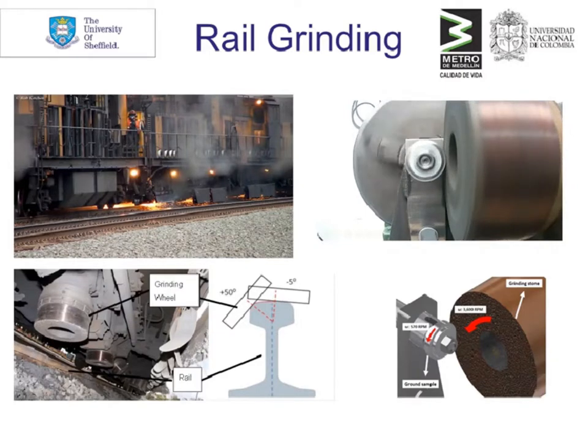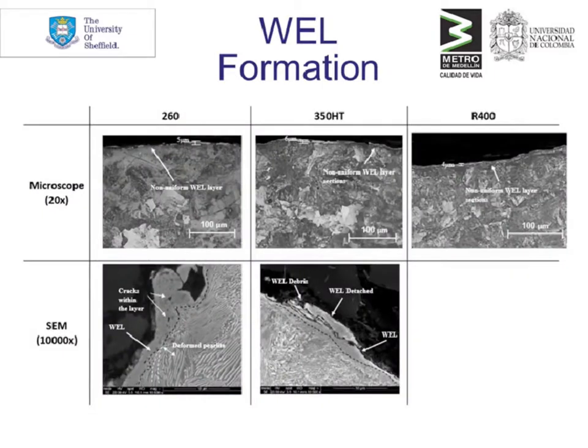You can see the rig starting to run here. So grinding stone spinning at 90 degrees to the disc, so we can actually grind the disc. And this can be carried out at different forces, speeds, and so on. Afterwards, we can section and look very carefully to see what levels of white etching layer have formed.